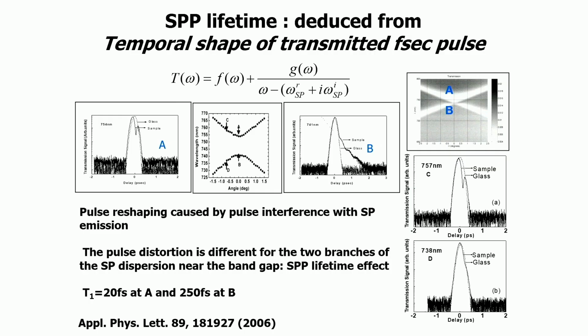Accordingly, with the broader line width and shorter lifetime, you see that the pulse distortion, the chirp, is within the pulse width. However, there is a long decay which corresponds to the plasmon lifetime. One is about 20 femtoseconds and the other is 250 femtoseconds in lifetime. This is just to understand some physics of these plasmon modes and how they interact with short pulses. I'll come back to this a little later, when we talk about broadband structures, and how this distortion can be overcome so we can couple short pulses and efficiently use this in other metamaterials.